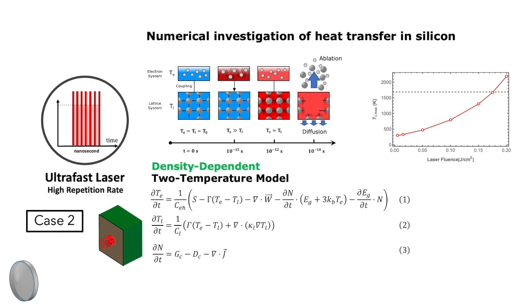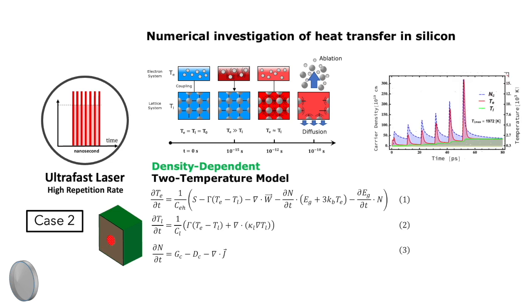Then we continue simulation to the multi-pulse case and show that even at low energy density, higher repetition pulses induce heat accumulation effect that can initiate ablation.